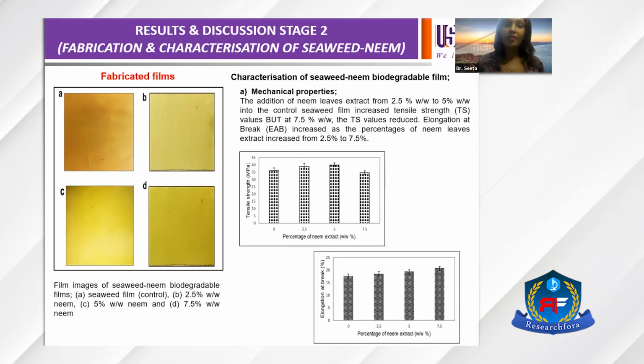From the characterization results, firstly the mechanical properties. You can see that the addition of neem leaves, up to 5%, increased the tensile strength. But at 7.5%, it decreased the tensile strength value. Elongation at break also increased.